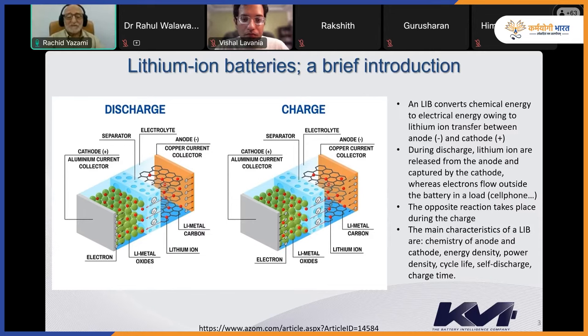Okay, so during the charge, when lithium is taken out from the cathode, the voltage of the cathode is increasing. And when the lithium is intercalated into the graphite, the potential or voltage is decreasing. So the difference between the plus and minus during the charge is increasing. It goes from about 3 volts to 4.2 volts at the end of charge if the cathode is an oxide, and between 2.8 and 3.6 volts if the cathode is based on phosphate.